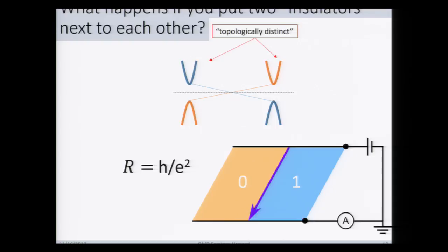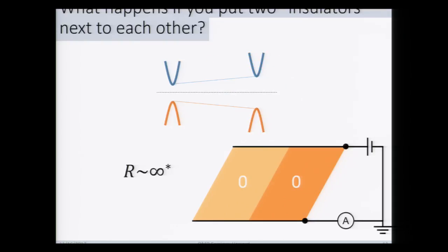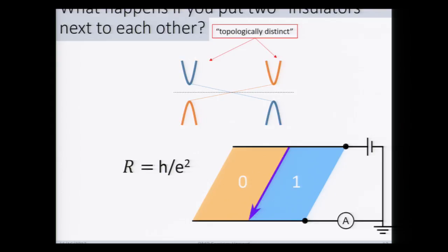Then let's imagine that we can have something that's not 0 but say a 1, something very different about this insulating state. We say that okay, these things are actually topologically distinct, and I'll clarify this word a bit later. But here in this sort of schematic band structure, we have a conduction and a valence band, and the color is meant to signify something about, say, the orbital structure that is changed across this interface. And in this case, where we have, say, a two-dimensional insulator with this number that we'll call a Chern number, and you have a difference of 1 across the boundary, if you do this ultra-simple two-terminal measurement, you have this arrow that represents a chiral mode that will give you a two-terminal resistance of h over e squared.